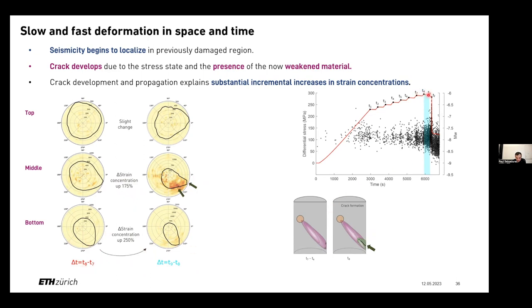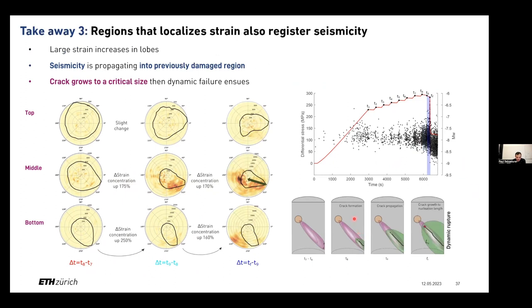So between this frame and this frame, we see a 175% increase in strain concentration at this location here. So we see this potential crack moving back through, and then what we think happened is the seismicity started to back propagate up, like you saw in the video, and potentially the crack itself reached a certain size that the total stress and energy in the sample was not able to be supported by the weakened material, and the dynamic rupture ensued, which is what we saw here.